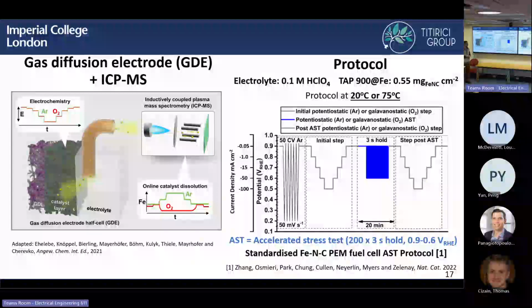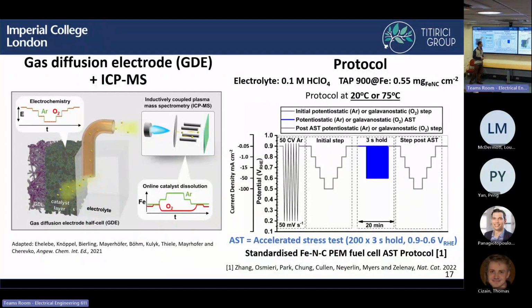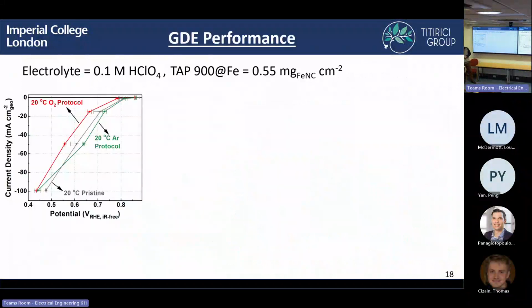And yeah, as I mentioned before, we do this AST protocol to try and mimic what's now being proposed as the standardized method in testing these catalysts in a fuel cell. So if we look at the current density initially, we can see something very different to the flow cell. We can actually obtain relevant current densities for a fuel cell. So we can get up to 100 milliamp per centimeter squared. So this is 2 orders of magnitude higher than what we can get in a flow cell.